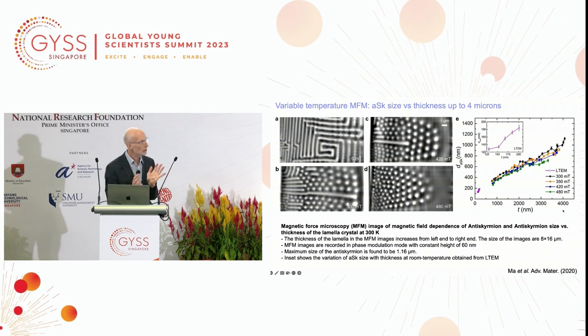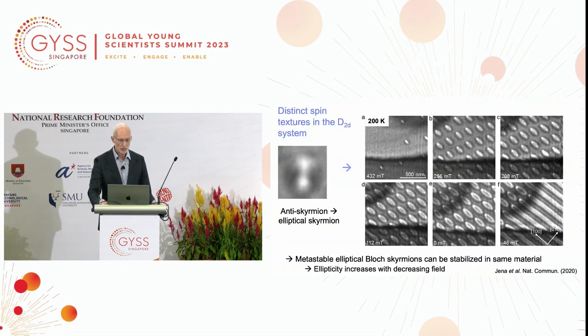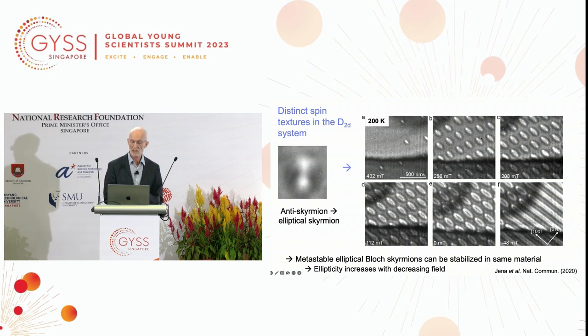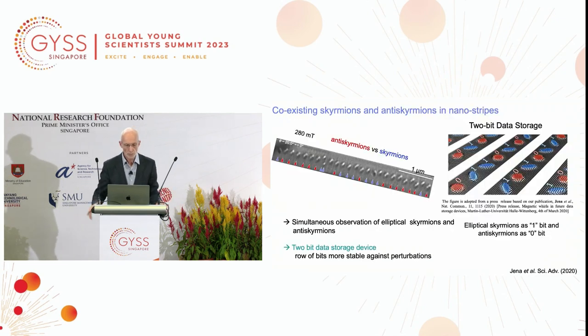Now, this whole area of science of these non-collinear spin textures has been very interesting in the last few years, and we ourselves showed that in the same material in which we can see these antiskyrmions, we actually can see another object. You see these elliptical objects where we can stabilize these objects because the wall now is entirely of a Bloch wall type, which has the lowest dipole-dipole energy interaction. So we can convert antiskyrmions into elliptical Bloch skyrmions, and one proposal we have is maybe we could build a racetrack where we store information not as the absence or presence of a domain wall, but as an antiskyrmion or an elliptical Bloch skyrmion. This will be very difficult to do, but we can see a combination of these objects experimentally, and of course we can simulate this using micromagnetic simulations.